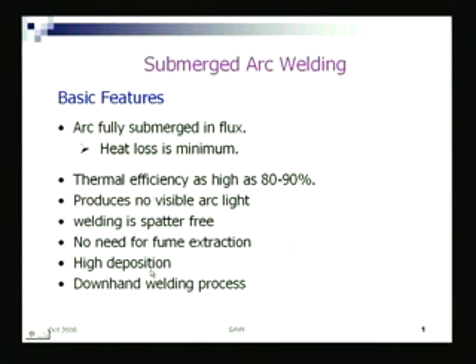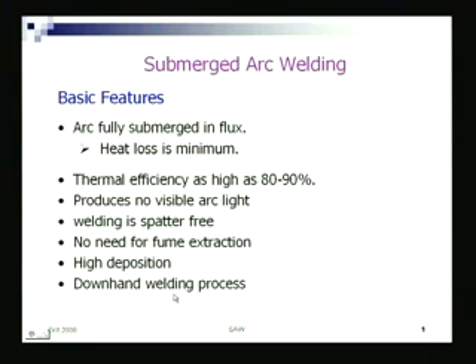One can have a high deposition welding. Why? Because this process is essentially an automated process, and being automated, I can use higher heat, higher current. Once you have higher current, you can go for a high deposition process. And it is another feature, it is always a downhand welding process, means it can weld only downhand, not positional welding like vertical or overhead.